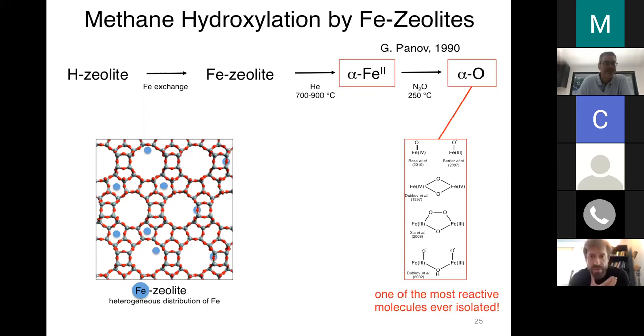Now, when you take this iron exchange zeolite and you heat it under a reducing atmosphere, like helium, to very high temperature, you form a reduced iron 2 site, which was known colloquially as alpha iron. And this alpha iron site will react with N2O at 250 C to form a reactive oxidant known as alpha oxygen. And alpha oxygen will react with methane instantaneously at room temperature to form methanol.